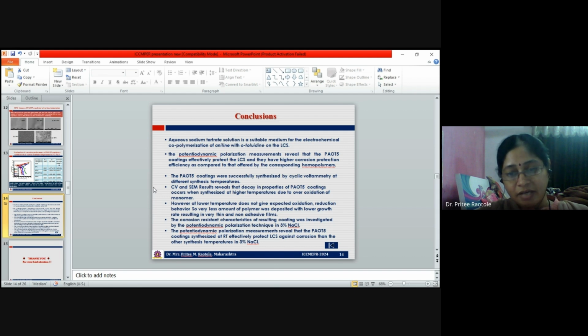The corrosion-resistant characteristics of the resulting coating were investigated by potentiodynamic polarization techniques in 3% NaCl, and the potentiodynamic polarization measurement reveals that the PAOTS coatings synthesized at room temperature protect the low carbon steel against corrosion more effectively than at other synthesis temperatures in 3% NaCl.